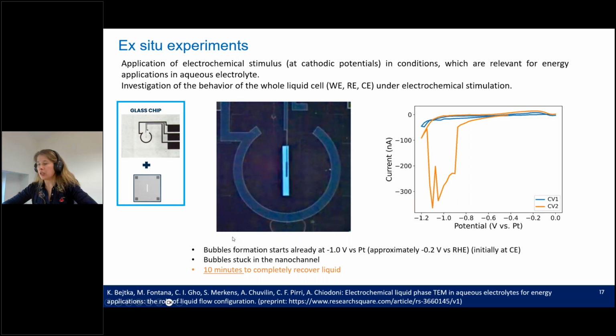This bubble is becoming bigger and bigger, and it's not efficiently brought away. We also see the formation of the bubbles in the area of the working electrode, where the bubbles of hydrogen are produced. And we have seen that everything then is like a big gas chamber, and it saturates quite much the cell. We have seen that when the bubble is produced, when we go back with the potential to 0 volt versus platinum, the gas produced is still remaining there for quite a while. It actually takes 10 minutes to completely recover the liquid.